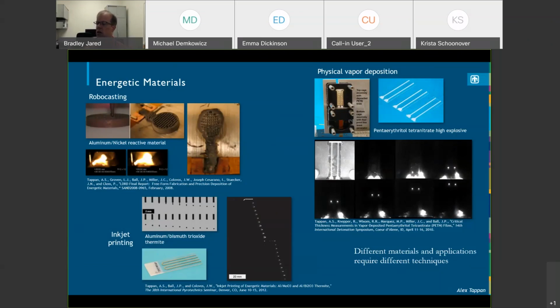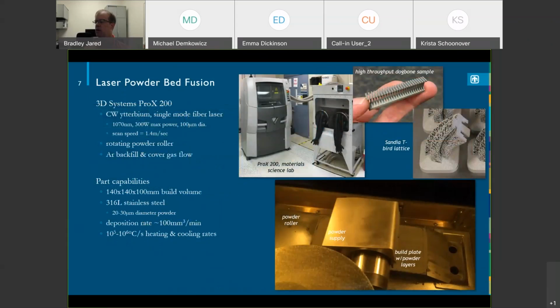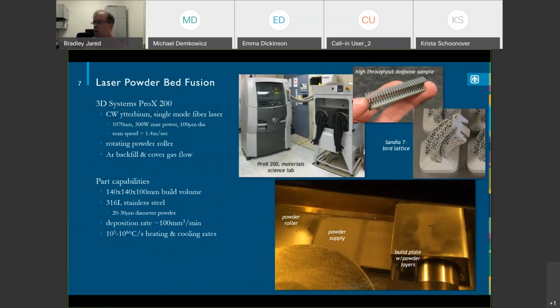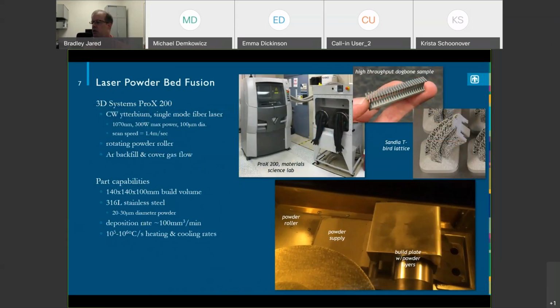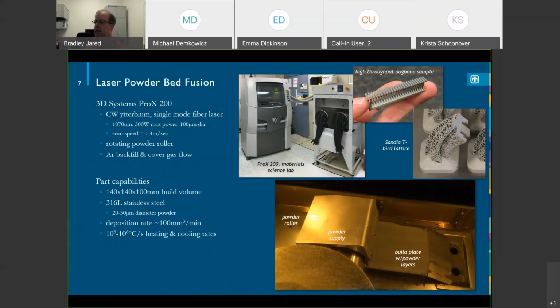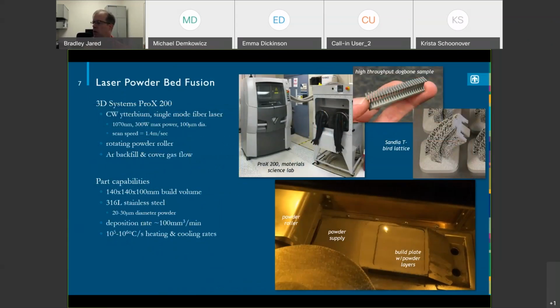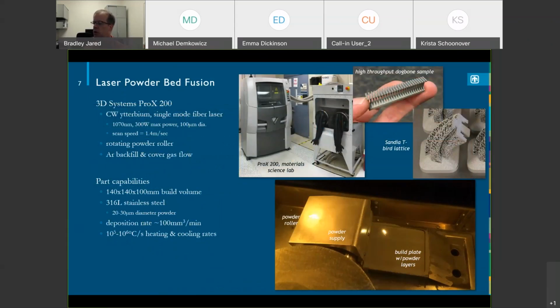You're not going to see a ton of energetic materials in the additive literature, although that's growing. The process I'm going to be working on and talking to you about primarily this morning is laser powder bed fusion. So this is a very popular metal technique. The machine in our lab where almost all these parts have been made is a ProX 200 by 3D Systems. It's a continuous wave ytterbium single mode fiber laser.